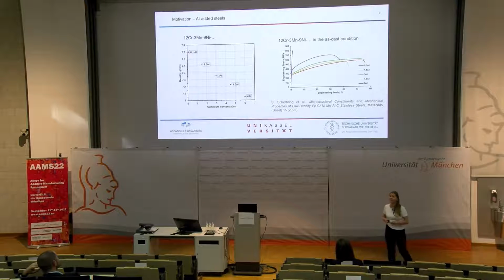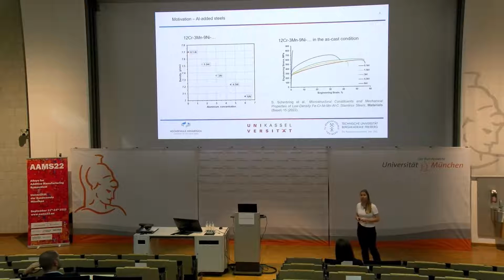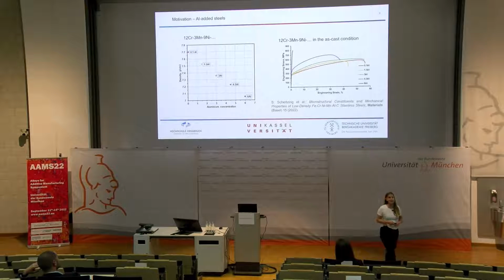So why would you use these in additive manufacturing? The idea behind it is that we have rapid solidification in additive manufacturing, and therefore nano-oxides of aluminium can be built up. Those nano-oxides might be able, as precipitates, to break up the columnar grain growth, and therefore we would have a more fine-grained microstructure and less anisotropy in our mechanical behavior. So this was basically the idea behind this.